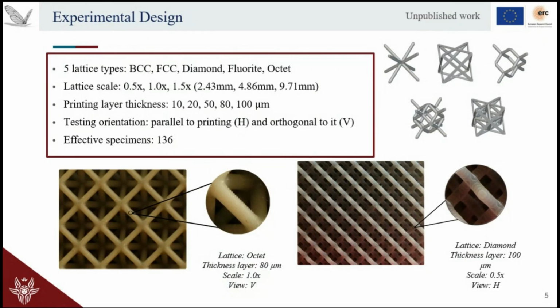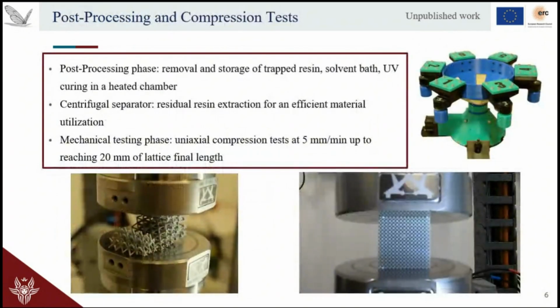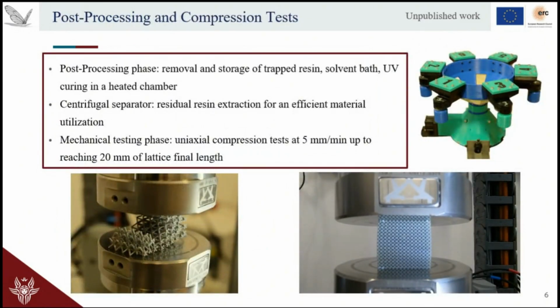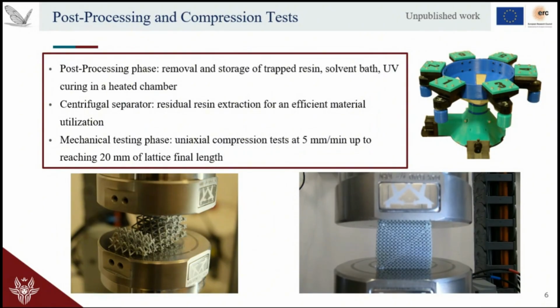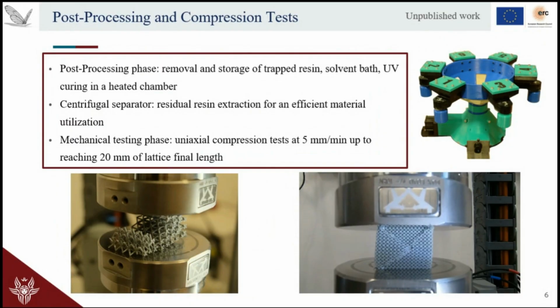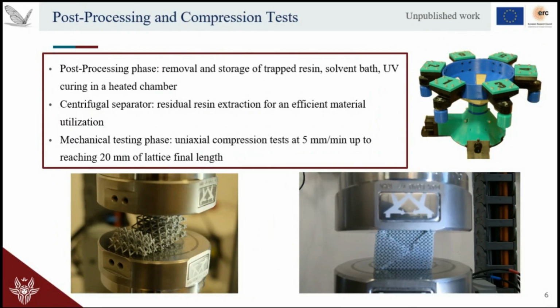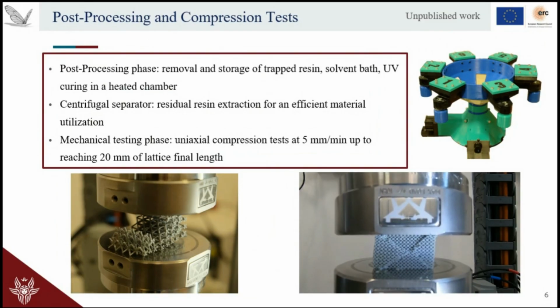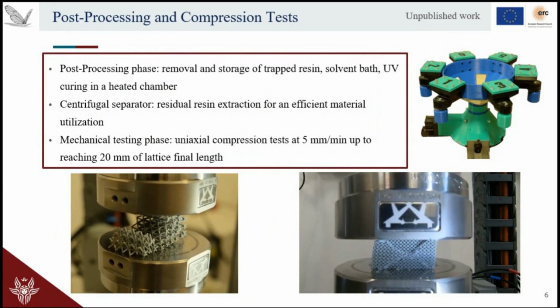We have tested the specimen both in a parallel plane regarding the print condition, and in an orthogonal way to capture the anisotropy inside the lattice structure itself. By doing this experimental campaign, we have gathered 136 data. So, as the compression test, we have performed it using a strain rate of 5 millimeters per minute until reaching 20 millimeters of final deformation. And upon printing, we had to do appropriate cleanup, since we are using vat photopolymerization.